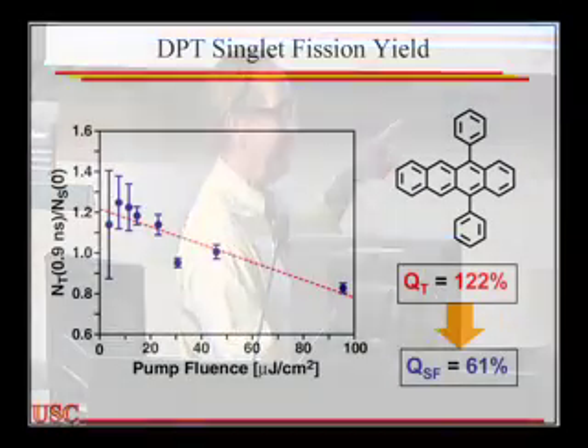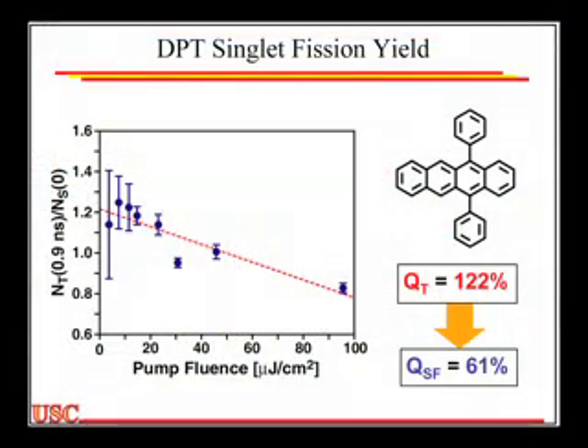Well, we can calculate what we expect at AM 1.5. And so remember, in our laser experiments, the intensity is way higher than it is in the solar part of the spectrum. So if we extrapolate back, so this is looking at the laser fluence, if we extrapolate back to what we expect, solar is right in this region someplace, and so if we estimate what the efficiency is, we're getting about 122% yield of triplets. So this is a singlet fission efficiency of about 61%.